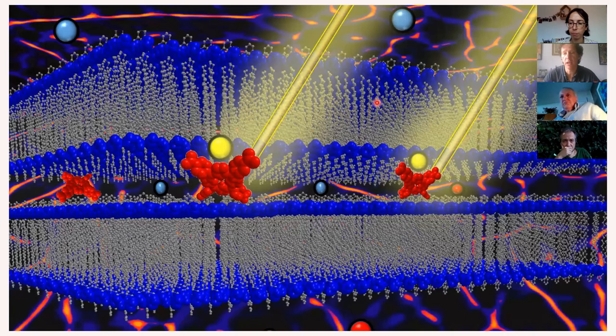The width is a lot more difficult to control, I would say, because of the growth process. But there are fibers that are very, very narrow as well. So you can influence it. We've shown that with temperature or with solvent composition. So the typical kind of things you do for a bulk heterojunction as well, influencing those things and the growth rates. Yeah, thanks for the question.